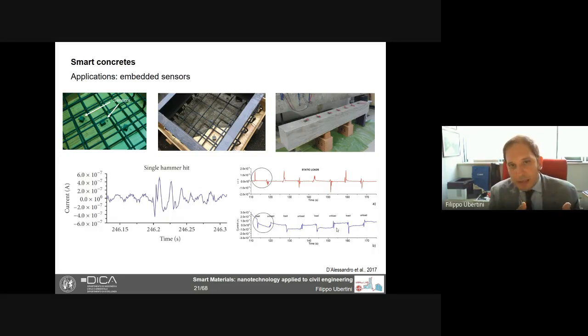Then we have made an experiment like the one before, hitting the beam with a hammer, and you see a typical decaying vibration obtained with the smart concrete sensors in the bottom left. Also, if a student goes on the beam and stays on the beam and then steps down and then steps up and so forth, loading and unloading the beam, you get very nice evidence of the increasing compressive strain through the output of the sensors in the blue line, while if you use the strain gauges, this is not so evident anymore. Strain gauges are with the red line.